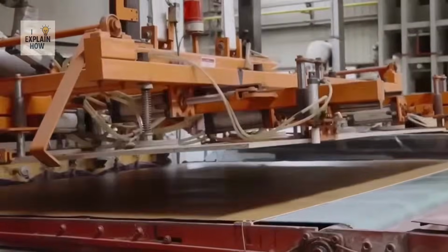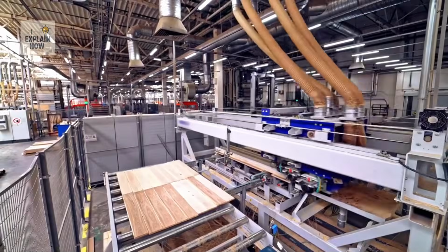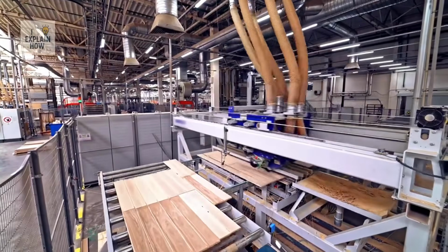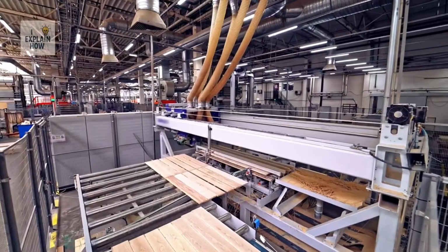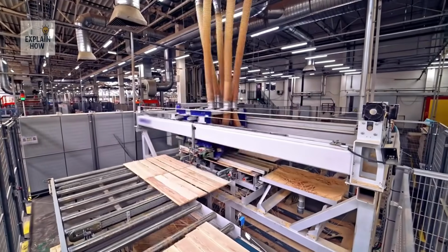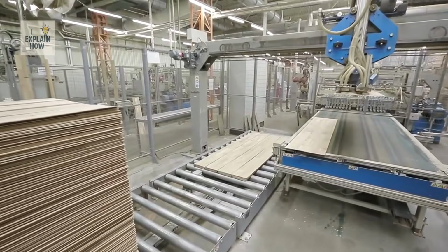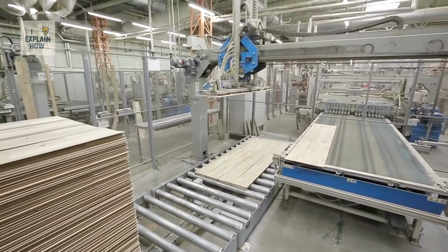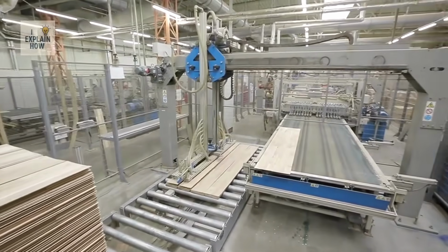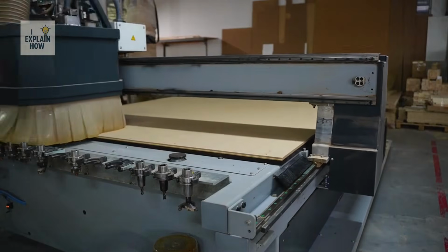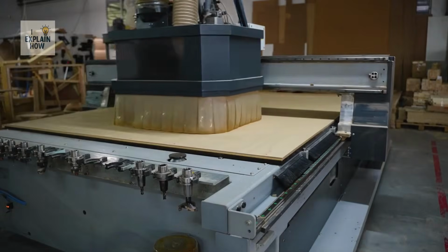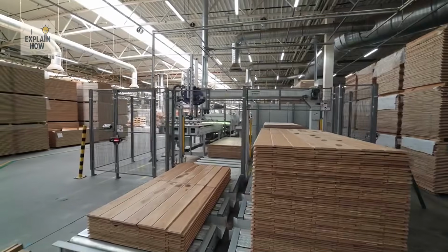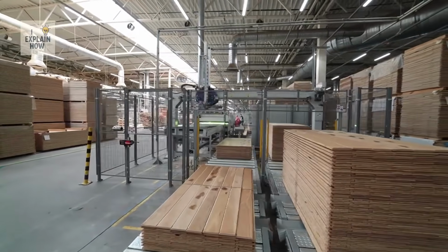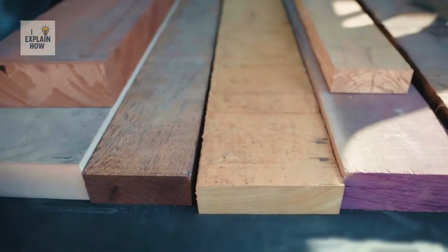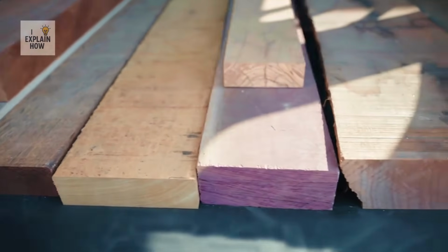This is the key part of the process, hot pressing. In continuous or multi-opening presses, pressure of several dozen kilos per square centimeter compresses the chips. At the same time, the heat of plates at 200 degrees Celsius triggers the resin polymerization. In just a few minutes, the soft mat becomes a solid monolithic panel. These burning panels are then slowly cooled in step coolers. Controlled cooling prevents deformations or internal stresses.